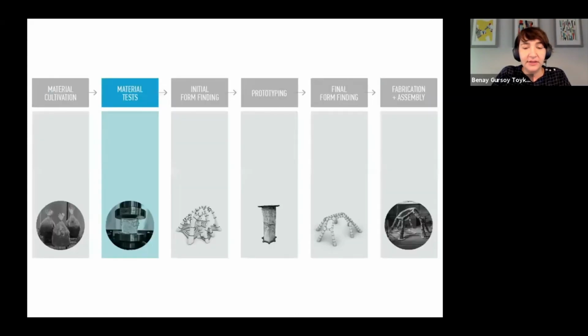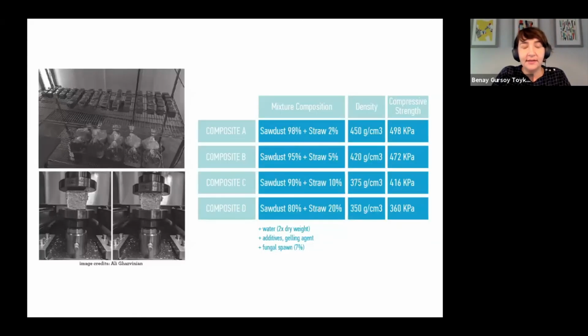So, material tests. This is part of Elise's PhD dissertation. He developed 35 different samples and tested their compressive strength. The difference between these samples was the sawdust to straw ratio. That was one thing. Another difference was how long they grew in bags versus how long they grew in formworks. So there were multiple parameters.